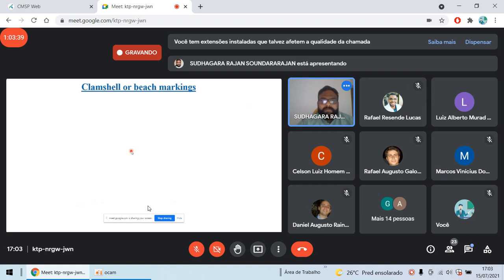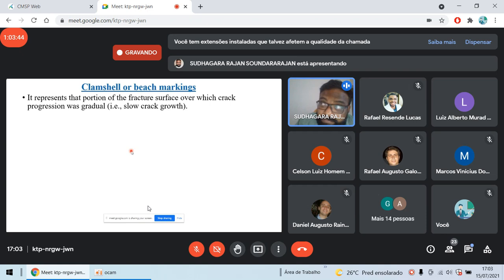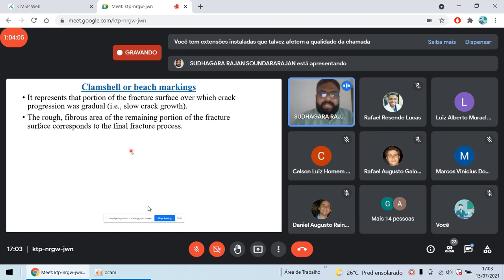The first feature we are going to see is clamshell or beach marking in a fatigue failure specimen. It represents the portion of the fracture surface over which crack progression was gradual. So if there is a region with a lot of clamshell marking, then that region is a gradual, slow growth region. The rough fibrous area of the remaining portion of the fracture surface corresponds to the final fracture. That's what we saw in the previous slide. The remaining area of the fractograph is the final fracture.